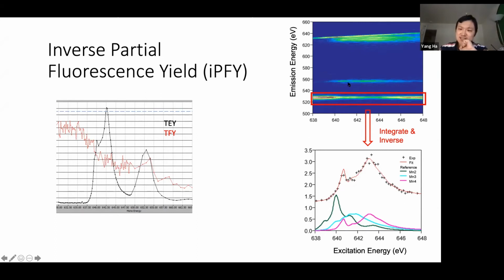But in this case, if you have a strong manganese absorption, the penetration depth of your X-ray is going to decrease dramatically, which will end up with less oxygen emission. So this dip really is highly correlated with the manganese absorption. So if we take the integration of just the oxygen emission, and we take an inverse of that, we will have a non-distorted manganese L-edge. And this technique we call the inverse partial fluorescence yield, the iPFY.